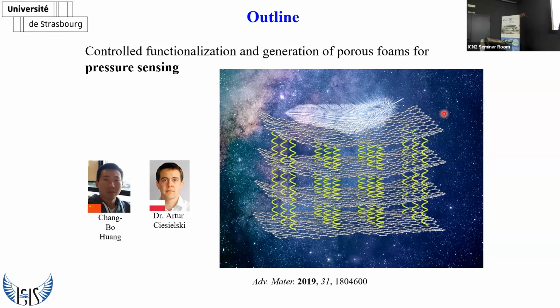The idea was to have a multilayer structure of graphene-based systems alternated by molecular springs, such that when we put something very light on top of this stack, it would compress the spring. My idea is that this distance, the length of the spring, should be tiny, below 2 nanometers. So we are in a tunneling regime. Minor changes of distance can bring a big change in the electrical readout.